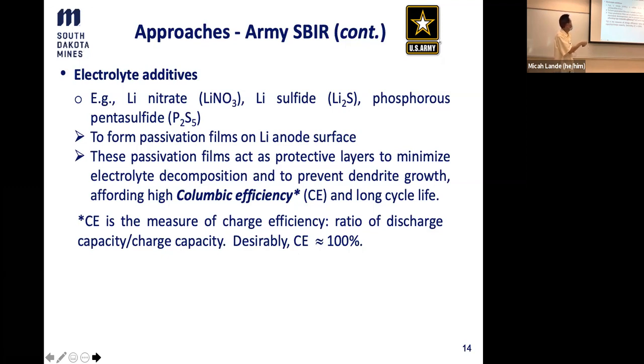One is some lithium nitrate and some polysulfide. The purpose for that is to form some passivation films on the lithium anode, so that it provides a protection layer to minimize the electrolyte decomposition and to prevent dendrite growth, and then to achieve the high Coulombic efficiency.